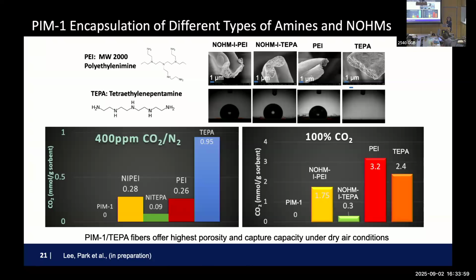When we looked at that, one of the things I wanted to do, by putting PIM outside, is that PIM is very hydrophobic. Most of the materials that love CO2 also love water. So if we can minimize picking up water while capturing CO2, that's fantastic. I wanted to design this fiber material to selectively reject the water while letting CO2 in. So hydrophobicity on the surface of this fiber was very important. As you can see here, when you have PEI, or even NOHMs encapsulated in this PIM, hydrophobicity is still good, and the NOHM-based ones are fantastically hydrophobic. But TEPA is so tiny that it migrates to the surface, and you no longer have a hydrophobic surface.